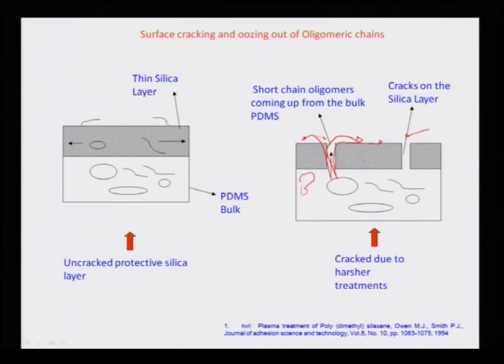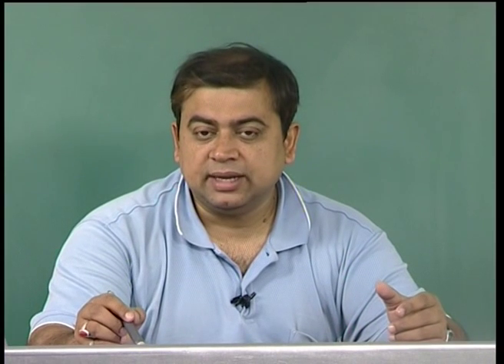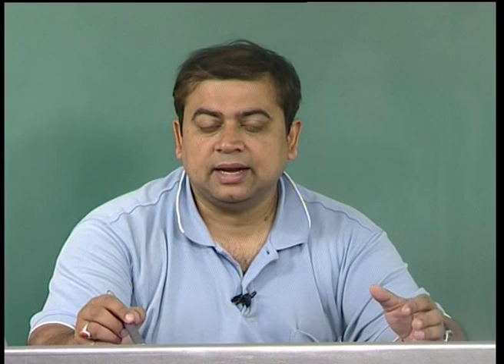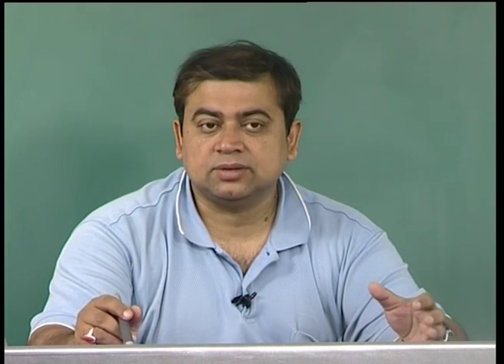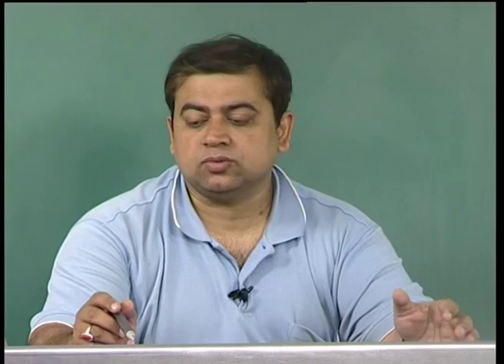The bonding between surfaces is therefore an immediate process. Whenever OH groups are just formulated on the silica layer immediately after oxygen plasma exposure, that is the right time for bonding between the surfaces. If you delay or wait, hydrophobicity recovers and methyl groups crowd the surface, ruining the bond strength. That is how polymeric bonding in MEMS can be realized, and that brings us to the end of today's lecture. Thank you.